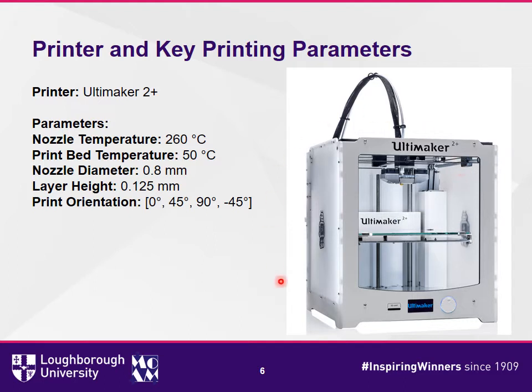The Ultimaker 2 Plus printer was used to print the samples for testing, and the following key parameters were selected for the printing process. The nozzle temperature was 260 degrees Celsius because of the high melting point of the material. The print bed temperature was 50 degrees Celsius for adhesion of the material with the print bed while printing. The nozzle diameter was 0.8 mm to avoid clogging issues, and the layer height was 0.125 mm to maximize the amount of fiber in the layers. Finally, the print orientation of 0 degree, 45 degree, 90 degree and minus 45 degree was repeated among the layers to achieve a quasi-isotropic structure.